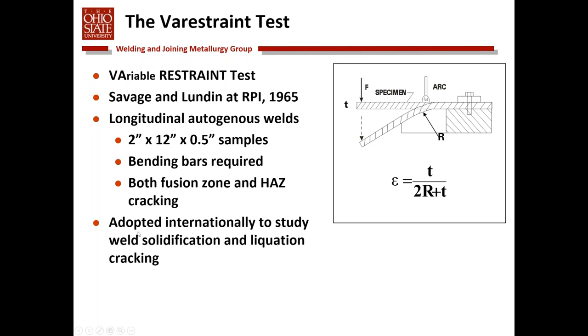The original test used fairly large samples, 2 inches wide by 12 inches long by half inch thick. Those samples often required bending bars to allow them to conform to the die block as you bent them around the die block as you made the weld. The original test would induce both fusion zone and heat affected zone cracking in the sample. And this test over the years has been adopted pretty much internationally to study weld solidification and liquation cracking.